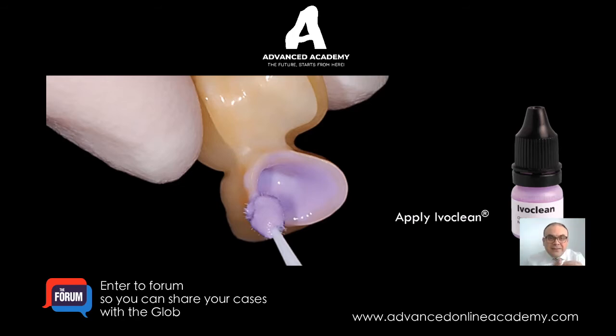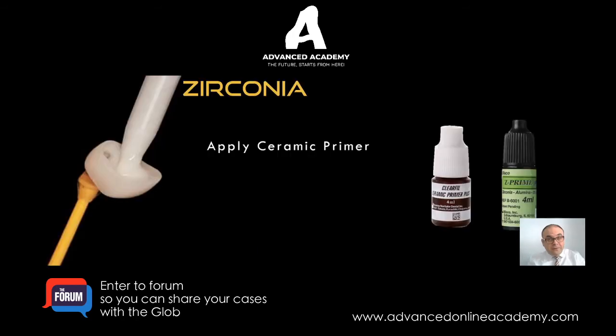You can't clean it with air or water steam, or phosphoric acid, or hydrofluoric acid. Nothing will clean it properly except IvoClean, which is one of the products that is available. Now there are two or three other products available from multiple manufacturers, all claiming the ability to clean zirconia very, very well. Using IvoClean after your try-in, you apply it for 20 seconds, and then you wash it, and then you apply your ceramic primer, and then it'll be ready for cementing.